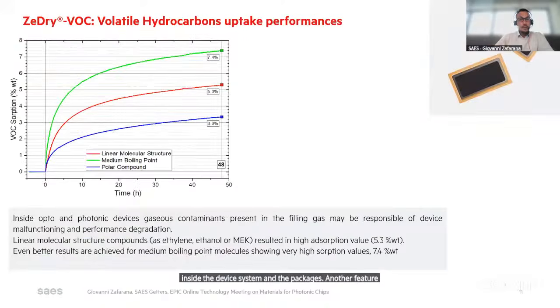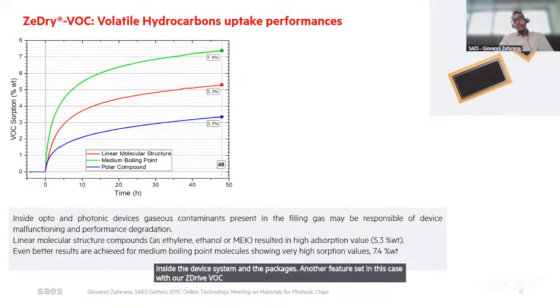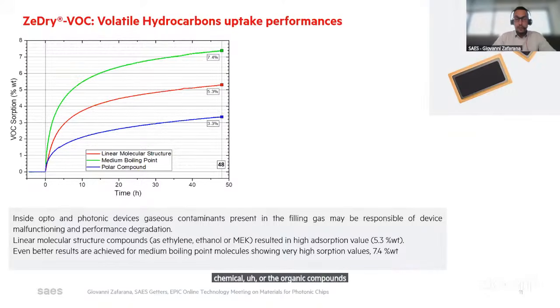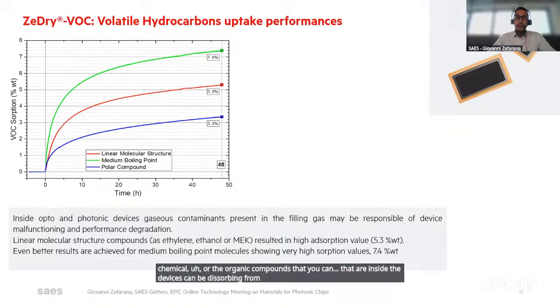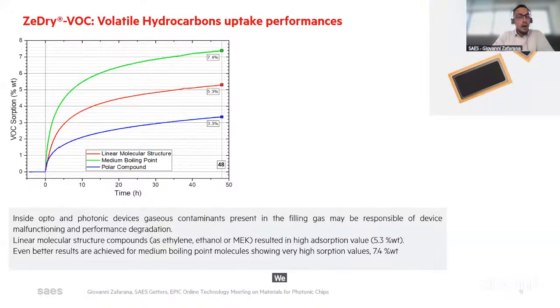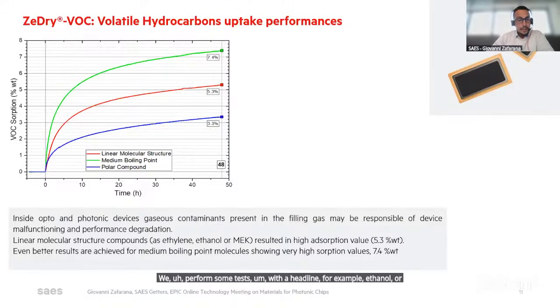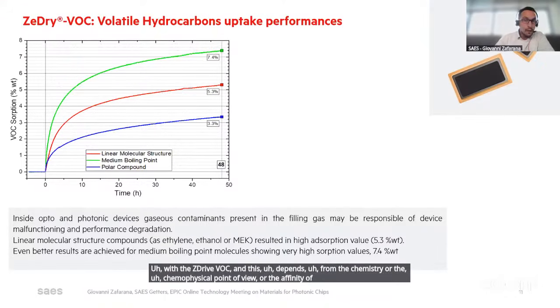Another feature, in this case with our Z-Dry VOC product, is the difference of absorption depending on the chemical nature of the organic compounds that are inside the devices and can be desorbed from polymeric materials. In particular, we perform some tests with ethylene, for example, ethanol, or methyl ethyl ketone, and we measure the uptake of these different organic compounds with the Z-Dry VOC. This depends on the chemical-physical point of view, or the affinity of the compounds with the polymeric resin that makes up our products.